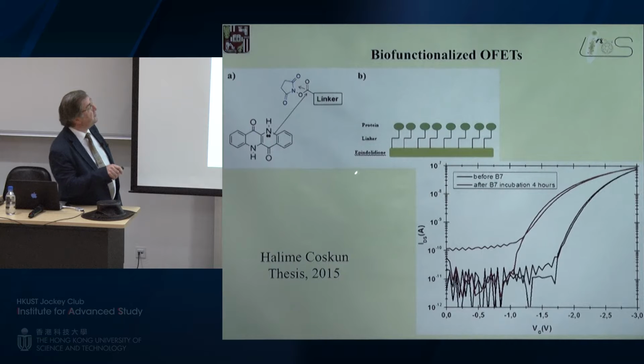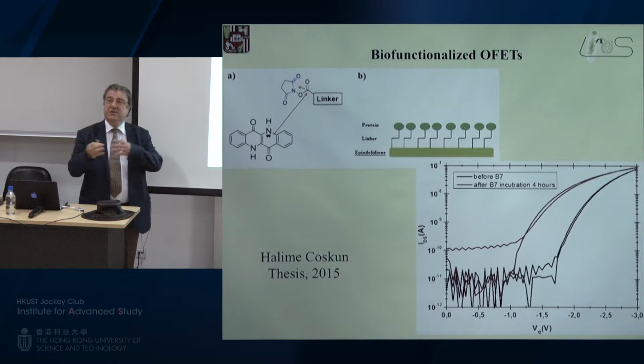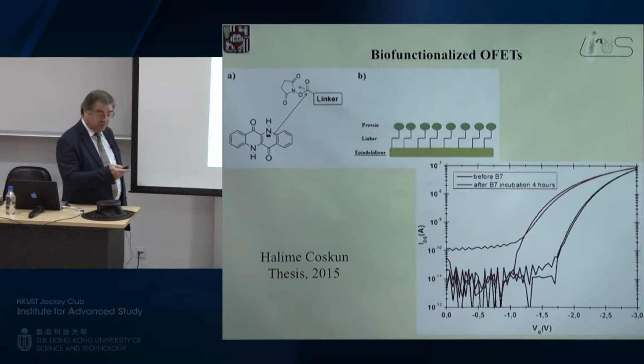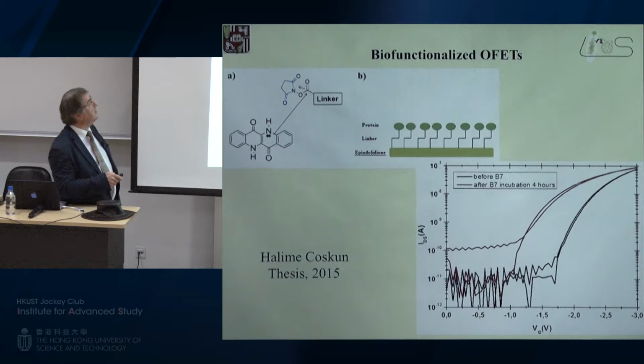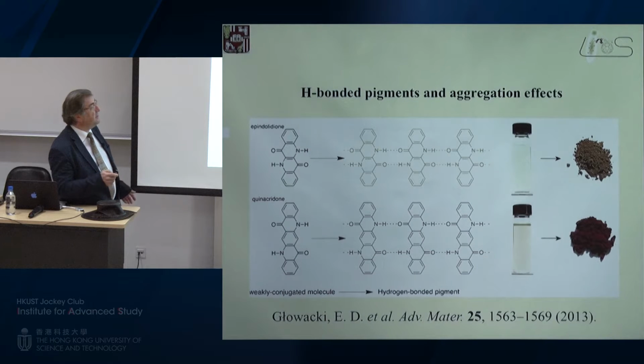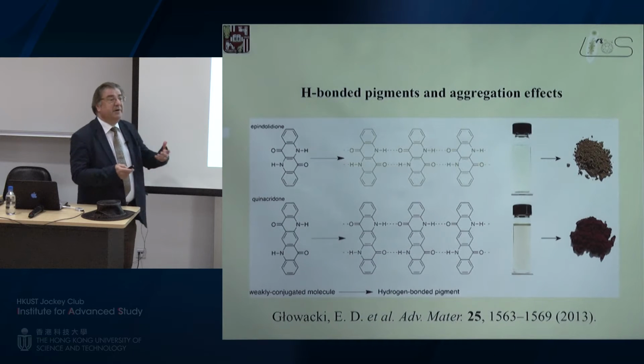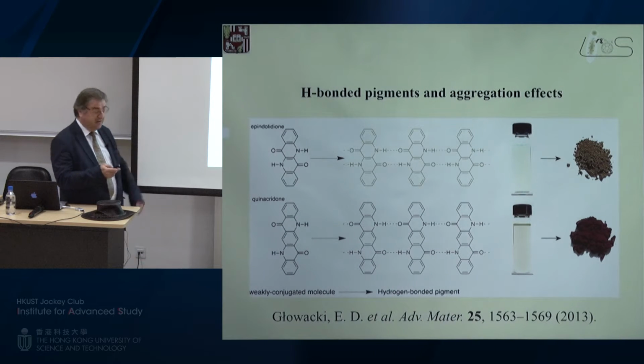So why is it so important? For example, we can surface functionalize these materials, and this opened up a new field, basically. We have several theses finished now. Papers are coming out. You can put all kinds of biotin, avidin type of plays. You can hook biosystems onto the organic semiconductor, and indeed, it's fantastically working. So I will come back in a minute to this a little bit, but these materials are really making beautiful, we call them pigments, which are making the color actually in more solid state effects.